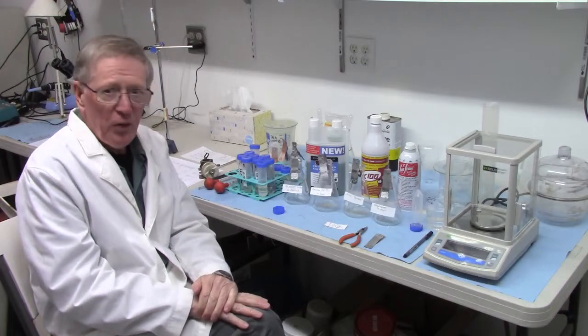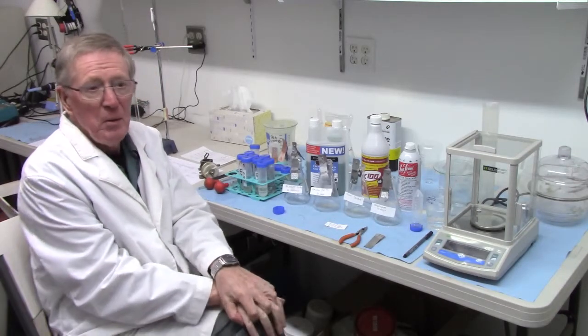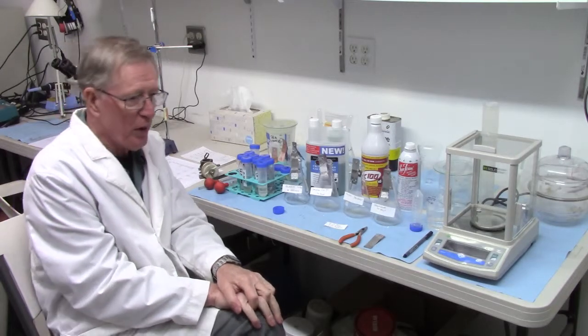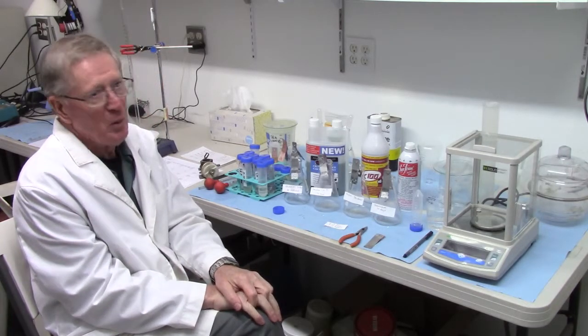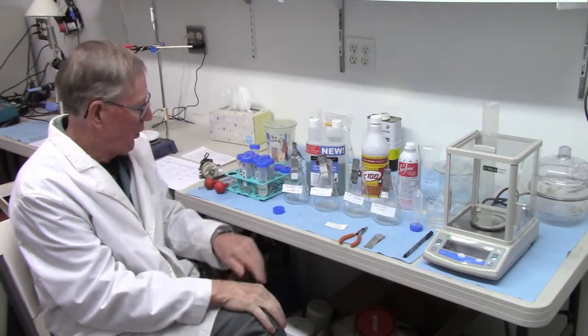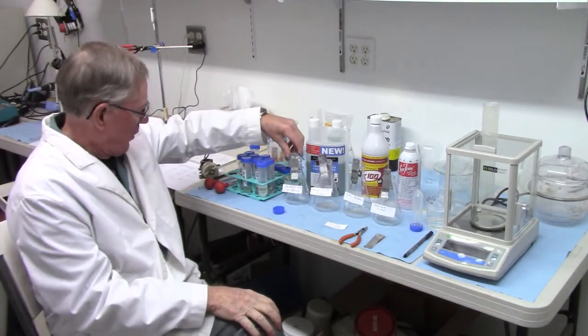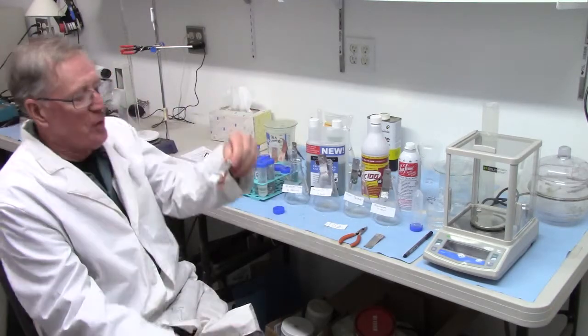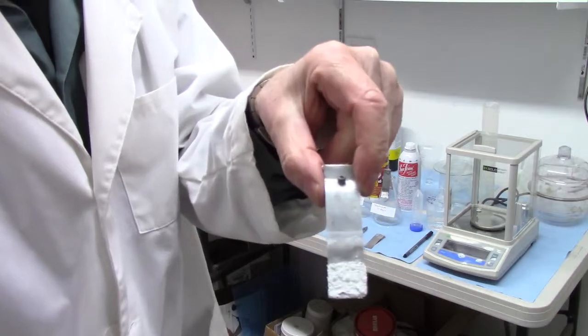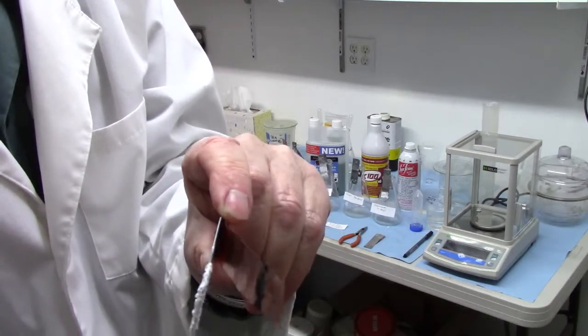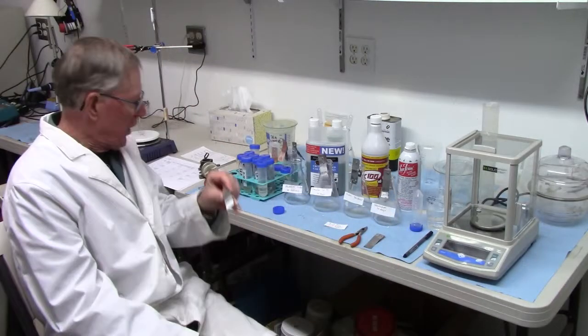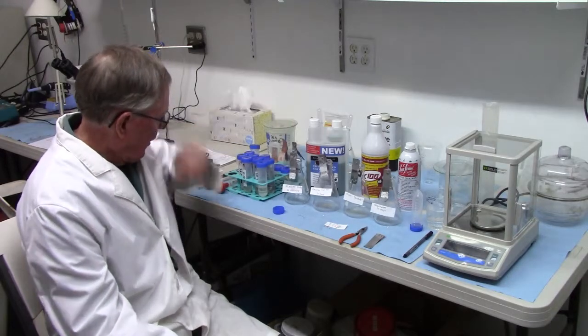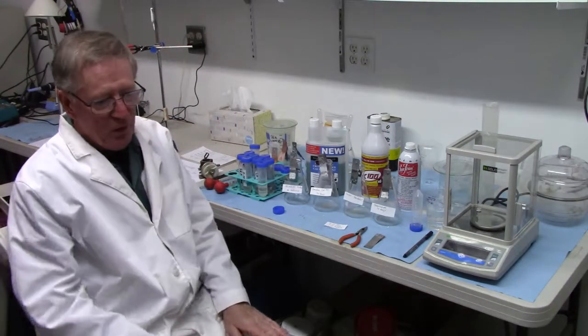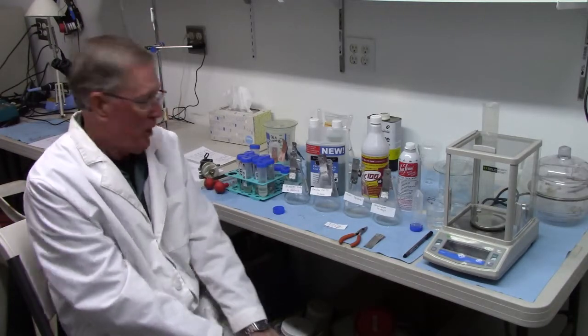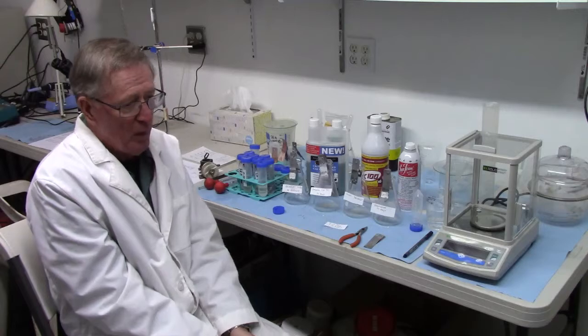Well, for you seafaring folks, you are interested in what happens when you get salt water in there. Boy, you don't ever want to get salt water in your fuel, let me tell you, after looking at these corrosion results. Because this is after 30 days. This is the blank. See all that horrible white gunge on there? Chemically, that will be zinc hydroxide. And if zinc hydroxide is exposed to the air, it will absorb carbon dioxide, and then it will go dark and form zinc carbonate.